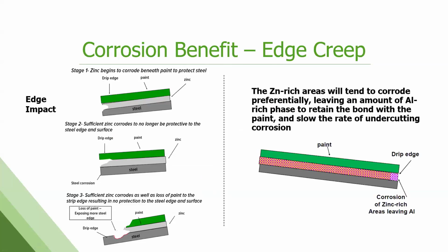Cut edge, same phenomenon on cut edge. So if you have a cut edge in an installation on galvanized, that zinc gets worn away. Now you have this flap of paint hanging out there that's got nothing to stick to. That peels back, exposing more zinc, more steel gets exposed, and it just becomes this vicious cycle that accelerates. On the aluminum zinc product, you're not going to have that. You're still going to have aluminum on the edge. Now, the aluminum zinc product, the Galvalume product, is going to corrode eventually, but just at a much slower rate.